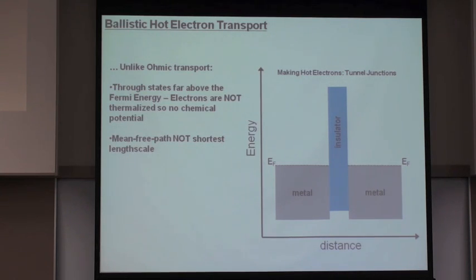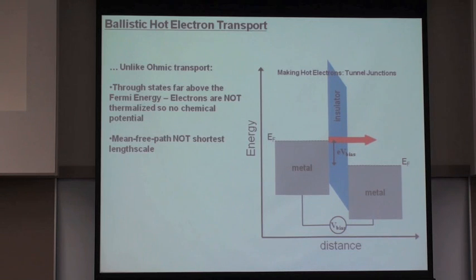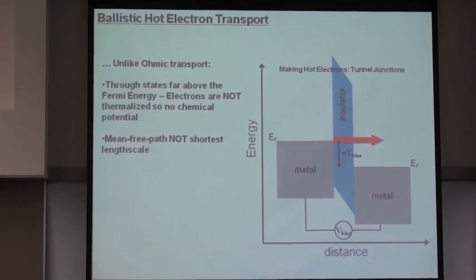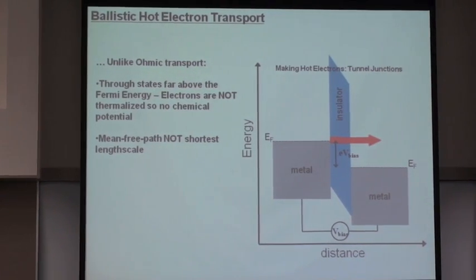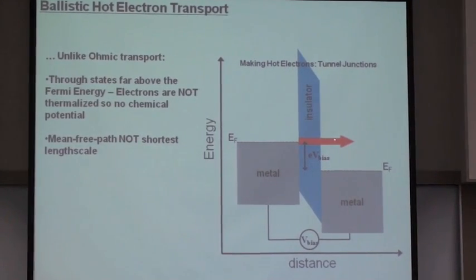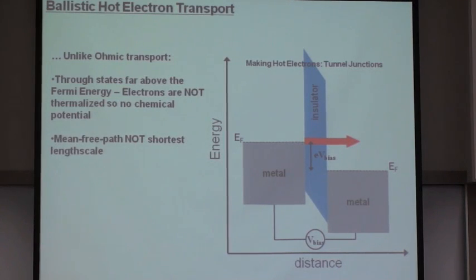When I apply a voltage between these two metals, what happens is that the voltage bias gives potential energy to electrons in the cathode relative to the anode, and then electrons can tunnel from filled states at and below the Fermi level into unfilled states. Electrons from the cathode at and below the Fermi level can tunnel into empty states at equal energy in the anode. And at that point, they have much more energy than the Fermi level in the anode, and they're not thermalized to it. These are hot electrons. Now, we make use of ballistic transport through this anode such that we can collect the electrons which can travel a certain distance on the order of the mean free path before they inelastically scatter down to the Fermi level of the anode.